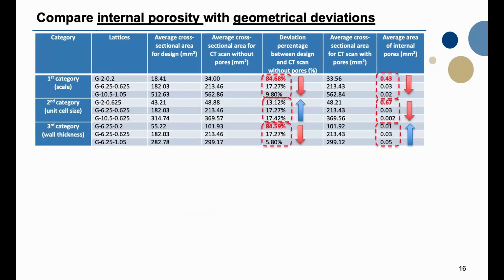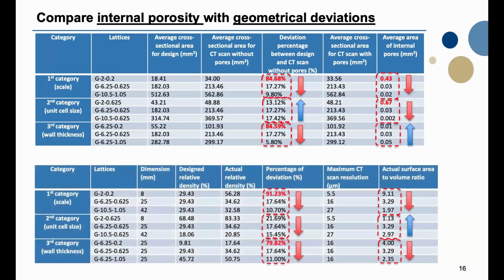And if we compare the internal porosities with the geometrical deviations, here we have a lot of data, but if you look at the highlights, as the scale increases, the percentage of deviation decreases significantly. And if you look at the area of the internal pores, the lattice with the smallest dimension, and also the second one, has a lot more pores compared to the rest. If we compare the internal porosity with the geometrical deviations, some of them show a similar trend, but some show the opposite trend. And for the geometric deviation, as I stated, the lattices with the smallest dimension, and also the lattices with the thinnest wall thickness, have the largest deviations here.